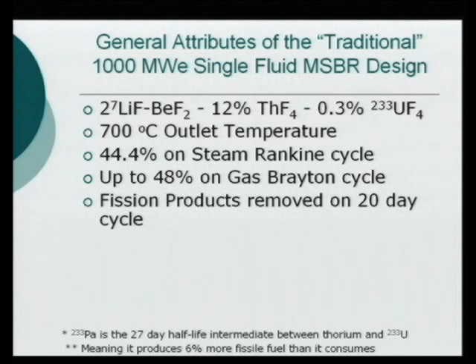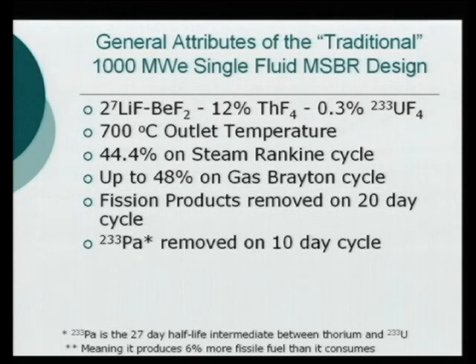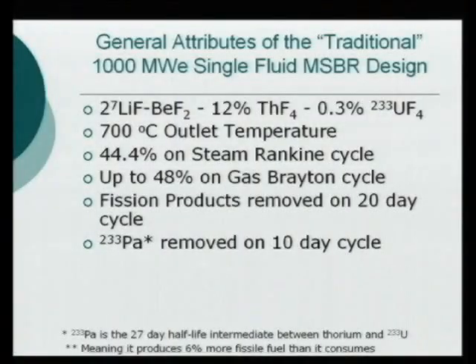Some were removed a little quicker, some a little slower, and I'll talk in a minute about how a lot of them come out automatically. Now, protactinium is sort of the intermediate between thorium and uranium-233. Thorium becomes protactinium-233, and that will decay to the thing we want, uranium-233, with a 27-day half-life. We often need to remove that, or in this case, we need to remove that for this design, which is a bit of a problem here. You want to take it out of the neutron flux so it doesn't take another neutron and not get to what you want. And I'll talk more about that a little bit later.